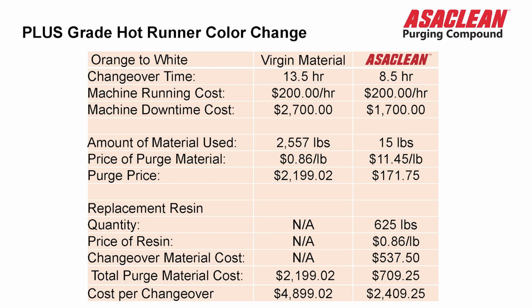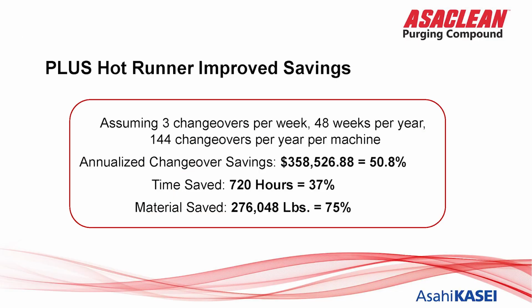When we used the Asaclean, we were able to reduce that changeover by 5 hours to 8.5 hours. And the bottom line cost associated with using the purge compound was $2,409 using 15 pounds of purge. Again, amortizing that out, 3 changeovers per week times 48 weeks per year, overall savings in that particular case was 50.8% or over $358,000. Time saved, 720 hours of valuable productivity we were able to give back to this client. Material saved, 75%. Pretty impressive numbers.